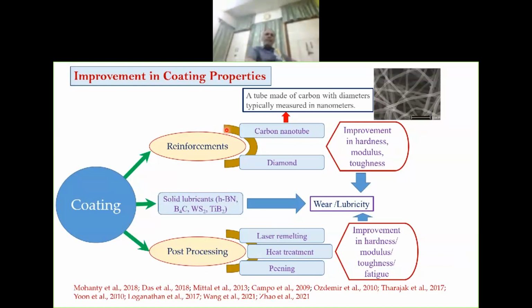Can I further improve it? There are mechanisms. You can produce something that gives it hardness, stability, and strength. For example, you can put in carbon nanotube, you can put in diamond, and you have good wear property. Add to it some solid lubricants that will give you lubricity as well. You can take an as-sprayed coating and post-process it using some laser remelting, heat treatment, or shot peening. They are possible.